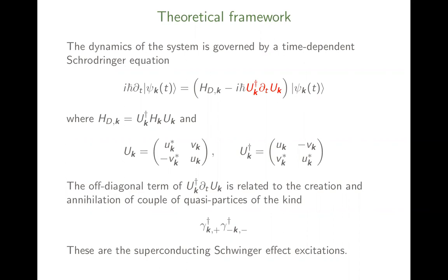I thought that it was difficult to get the electric field into the superconductor. So I will arrange to say that you are in a phase in which you have a gap, a very clear gap, and the electric field is there. No, but that's one problem. Actually, the problem was that the standard hint was that all the standard BCS superconductors are metal in the normal phase. So you assume that the electric field is not penetrating in a metal. And then you say, okay, we assume that the screening properties of the electric field are the same in the superconductive phase, and you don't care about the electric field.